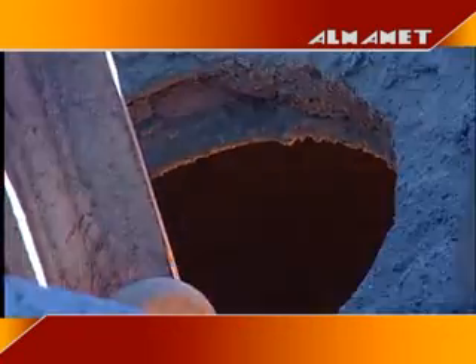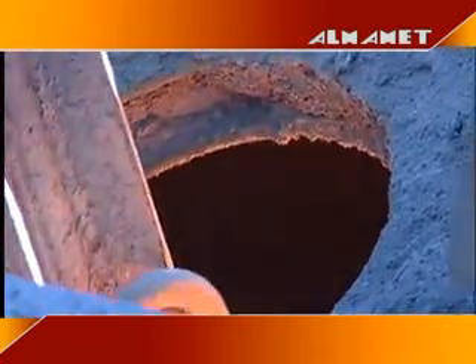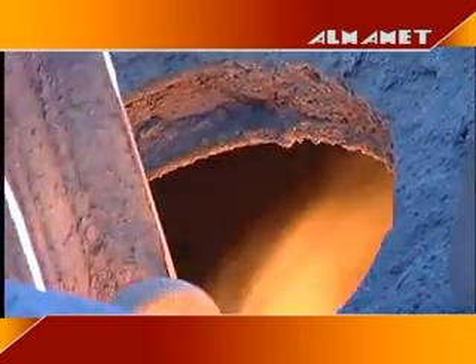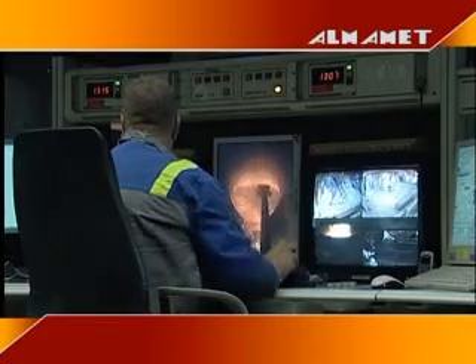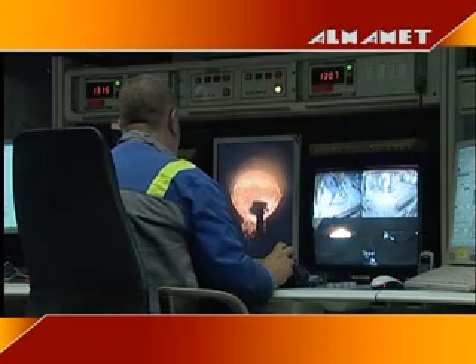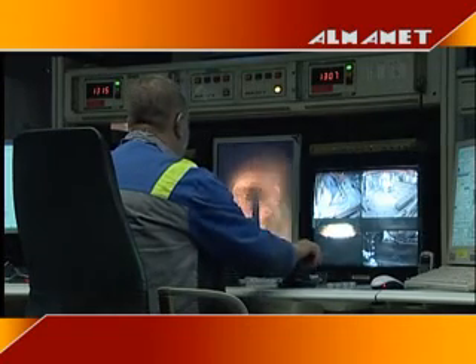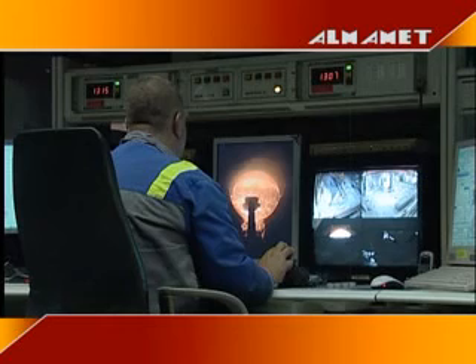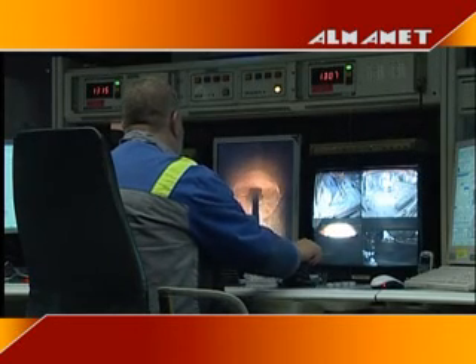By optimizing the injection ratio for the ideal proportion of magnesium, the resulting desulfurization quality is identical to that achieved by co-injecting magnesium and calcium carbide, or through the mono-injection of calcium carbide only.